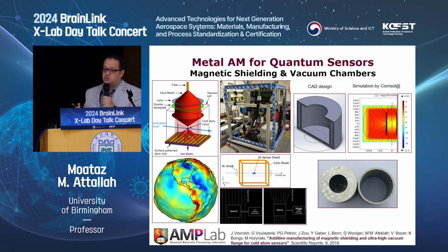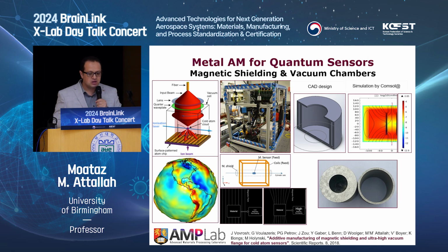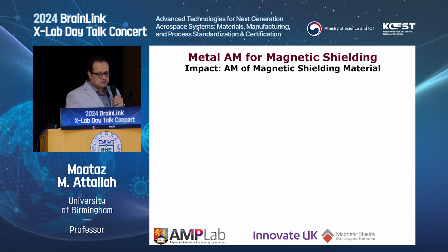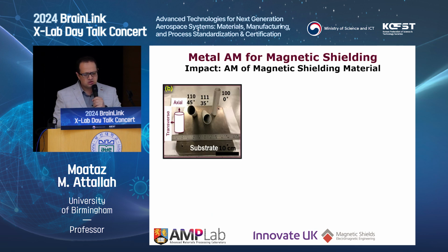It's a nickel iron alloy, so it's not too complicated to try to print it. And eventually we've done some tricks in the process to get it to work. We needed to do some tweaks in the crystallographic orientation of the material by printing it at a certain angle to allow us to get the maximum performance.